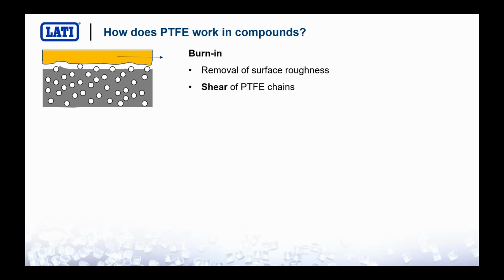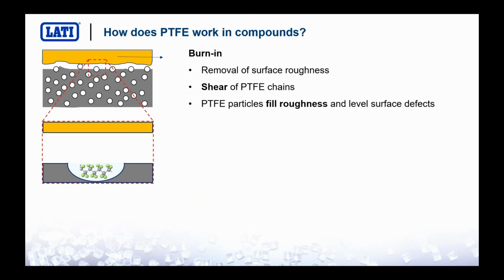Through the relative movement of one surface against the other, we have the removal of the surface roughness for sure. Due to the very low intermolecular forces, during this movement, it's very easy to shear the PTFE chains, which fill the roughness, so the valleys of these surfaces. Let's zoom on one of these valleys filled by PTFE, and you can see the white bubbles with PTFE inside.